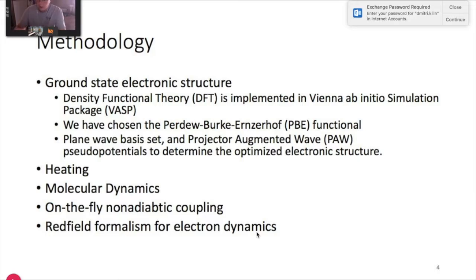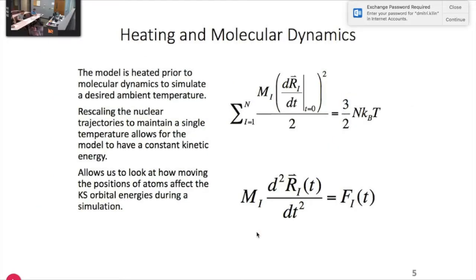And so through that, we'll be interested in the molecular dynamics, and so we'll run heating and molecular dynamics simulations, but then also using non-adiabatic couplings and a reduced density matrix formalism within Redfield for electron-phonon interactions and looking at dissipated energy of photovoltaic transitions. And so these are two equations that you saw earlier in terms of scaling the temperature and rescaling the velocities to get to an ambient temperature which we want to study, and implementing those as input for